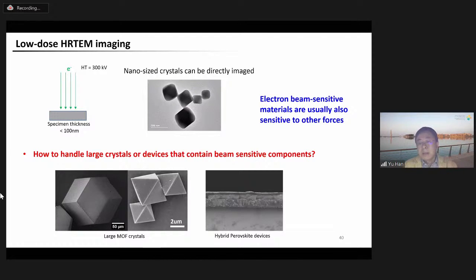Okay? So for sensitive materials, the specimen preparation is not easy because most likely the sensitive materials are not sensitive only to electron beam. They are also sensitive to other forces, and their structure can be damaged during the conventional TEM specimen preparation process. For example, some MOF crystals will become amorphous just simply by grinding or by crushing. Okay, so preparing a thin specimen suitable for TEM imaging from sensitive material is a challenge to be resolved.